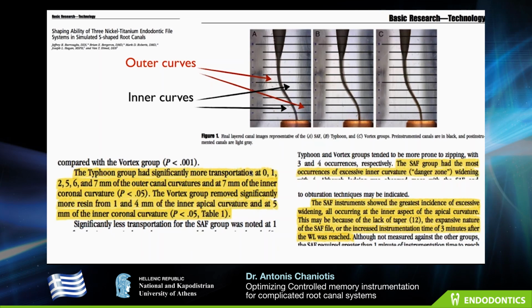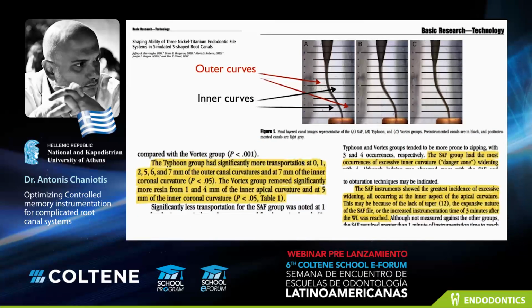While the vortex group, which is a heat-treated file but with restoring force, removed significantly more resin from 1 and 4 millimeters of the inner apical curvature, the danger zone. For the self-adjusting file group, check this out, it had the most occurrences of excessive inner danger zone widening. You don't want to have excessive inner curvature widening in complicated anatomies, right? Nobody wants to have that.